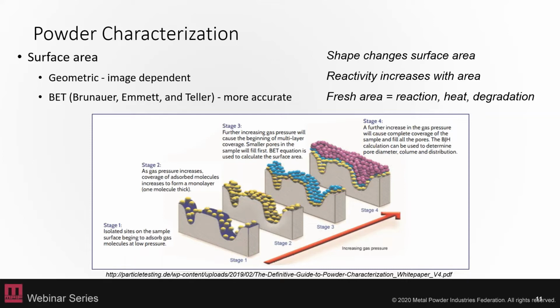And again, your shape changes your surface area, your reactivity increases with your area, and any fresh area that's formed, maybe as you're mixing these powders together, will potentially cause reaction as those oxides or whatever other surface might form, and can cause degradation as well as heating of the powders, and that's something you need to be careful of.